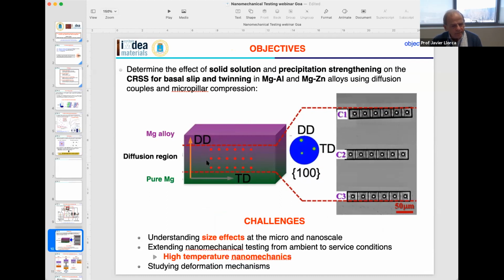So what you do is very simple. You have a slab of pure magnesium, and a slab of a given magnesium alloy, magnesium aluminum or magnesium zinc. You subject this to high temperature annealing, and then you create a diffusion region. In this diffusion region, as you move along it, you have different contents of the alloy. And in a region where the alloy content is constant, you use a focused ion beam to carve micropillars.